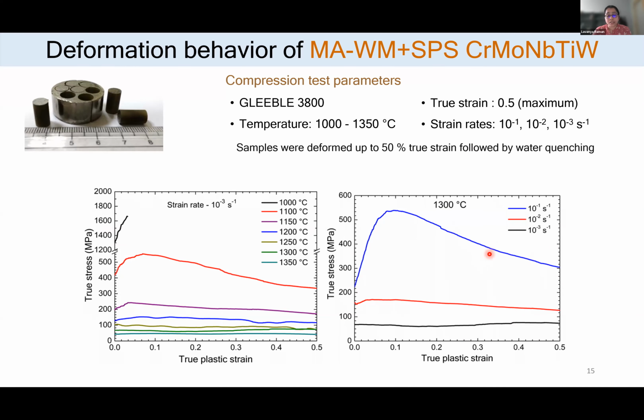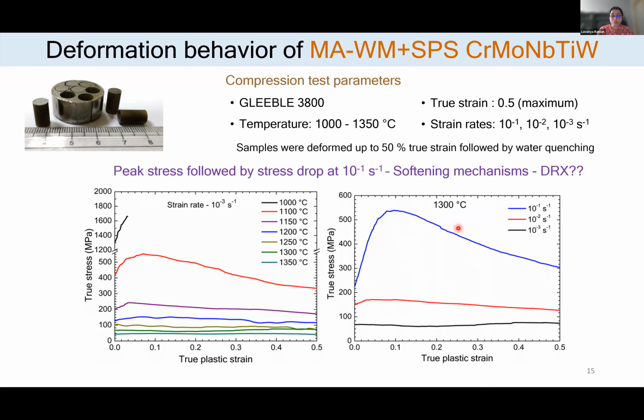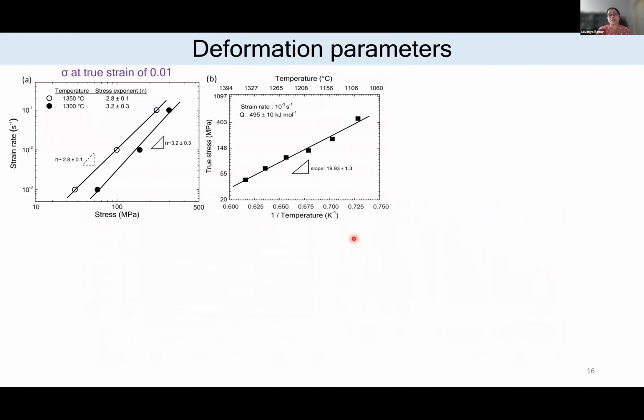From this stress strain behavior, we can see that there is a peak stress followed by softening. This kind of behavior is an indication for dynamic recrystallization to happen. But just from these graphs, we may not be able to say that for sure. So what we have to do is check the deformed microstructures. Before that, from these stress strain graphs, we can establish the deformation parameters such as the stress exponent and activation energy. Conventionally, these deformation parameters are calculated for the flow stress at a particular strain.